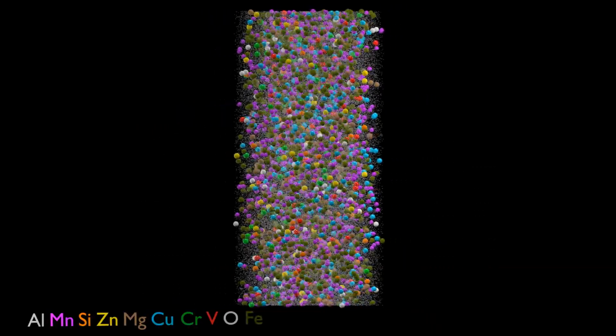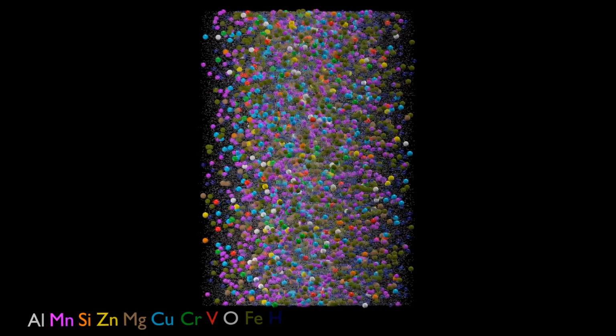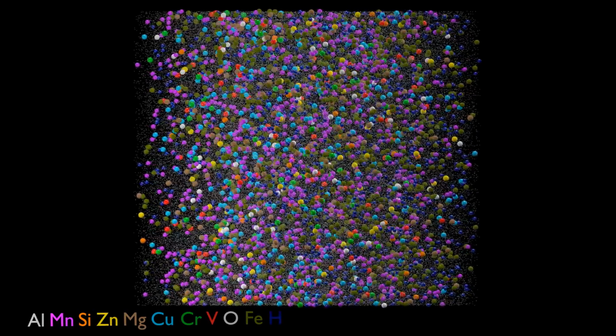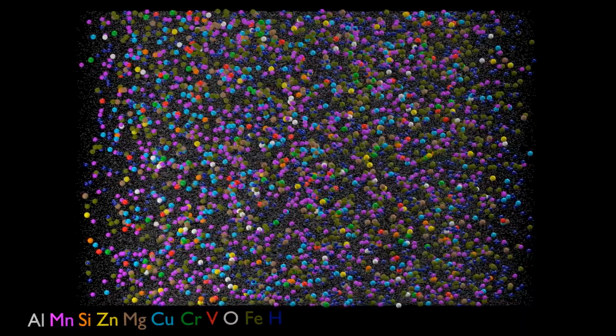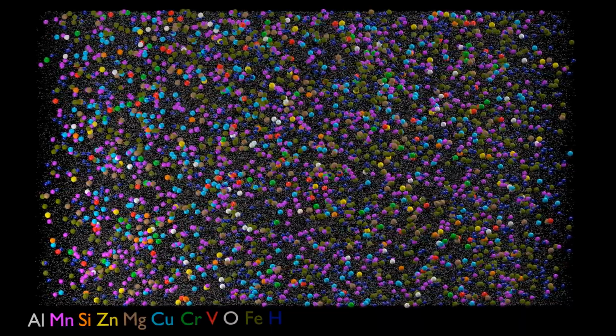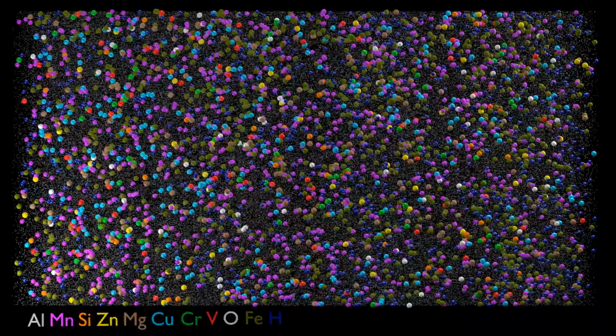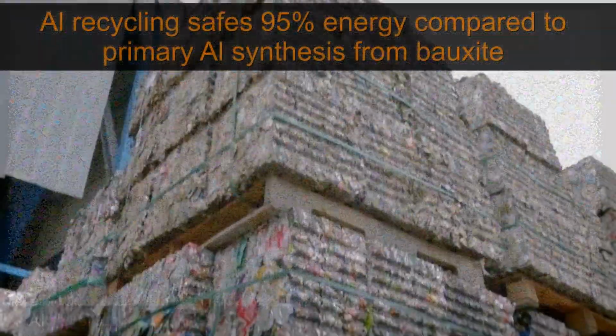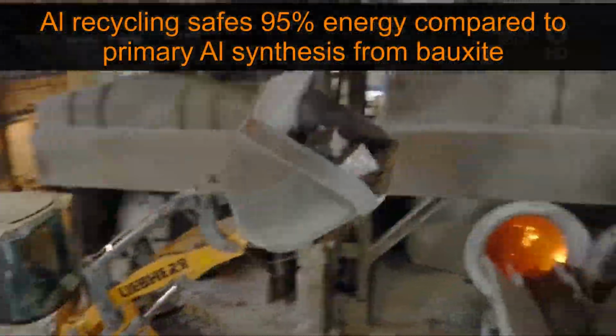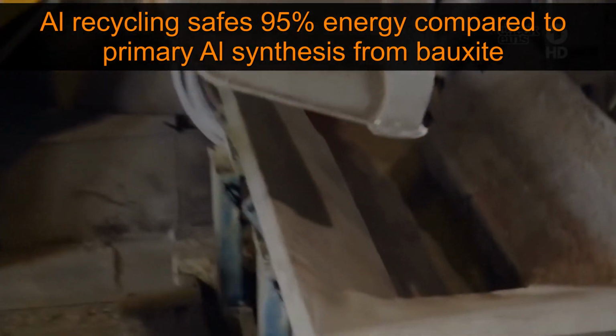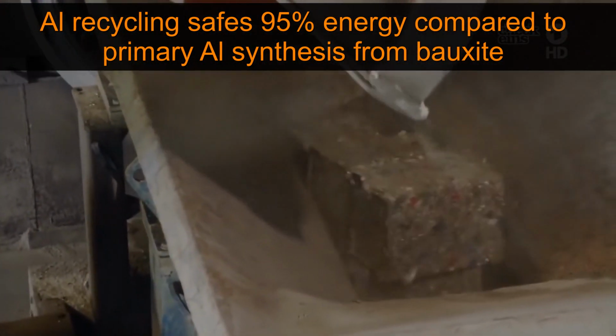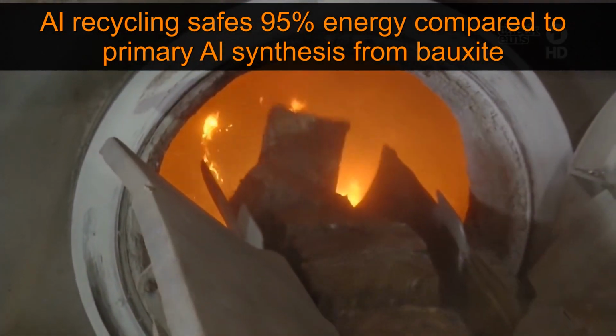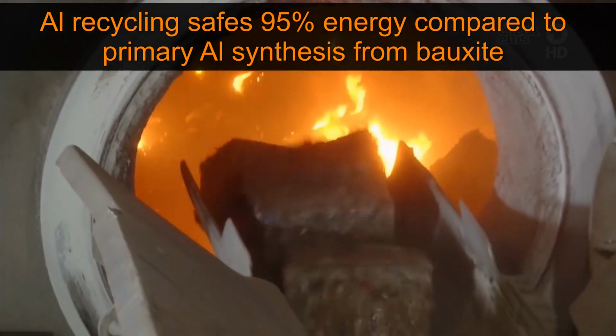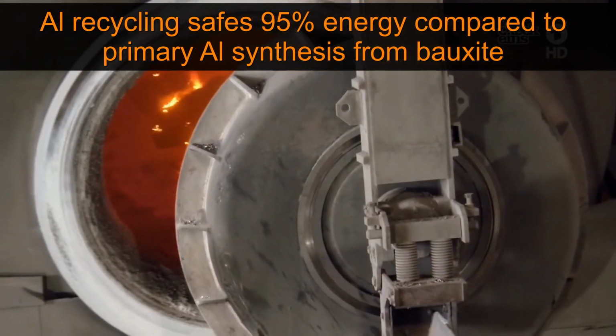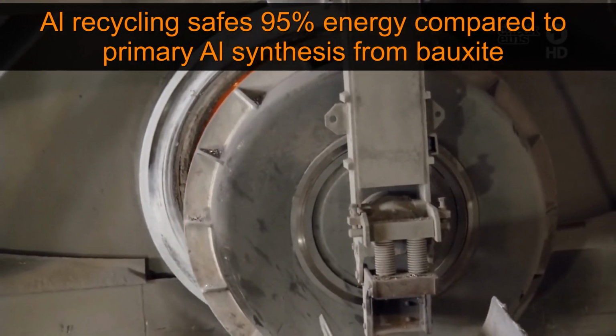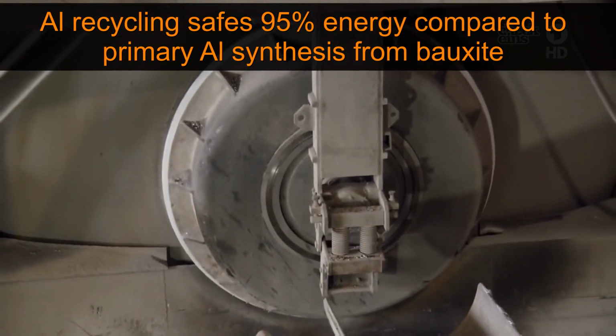The data show that besides the nominal alloying elements, such as about 1% manganese, 1% magnesium and a bit more than 0.1% copper, a number of further elements accumulate over the multiple recycling and remelting cycles it has been going through. It is therefore an important question in current research to understand how many and how much of these tramp elements can be tolerated in recycled aluminium alloys. A further question is, whether alloys can be developed, that are upfront designed for high impurity tolerance and hence, for high scrap usage.